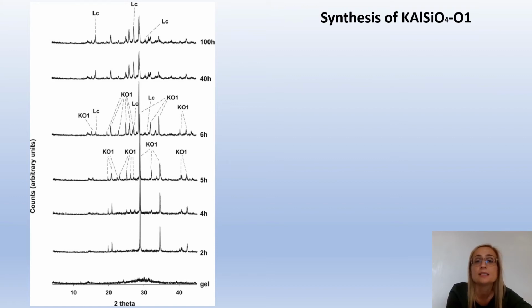A possible mechanism is that KAlSiO4-O1 would crystallize at first, then react with excess silica, finally forming leucite. Actually, replacement of KAlSiO4-O1 by leucite with time is consistent with the findings by Zheng et al. 2007. These authors, in fact, found kalsilite as the common metastable phase during the leucite crystallization process, when calcining at temperatures ranging from 750 to 900 degrees Celsius.